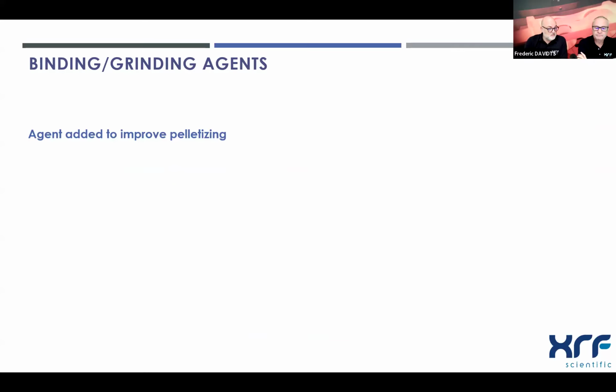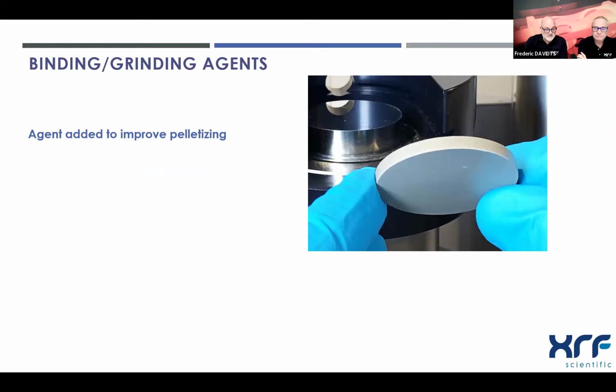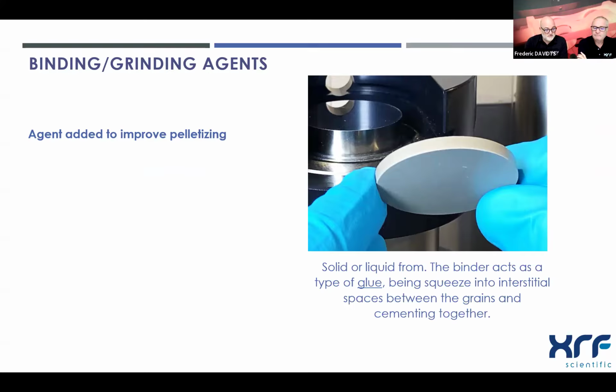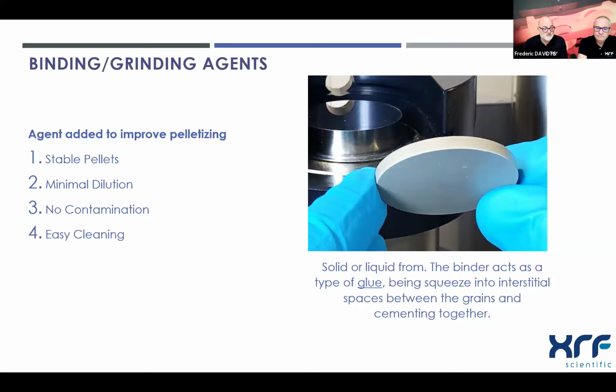So now let's speak about the binding and grinding agent. First, what do they do? Of course they improve the pelletizing. So we can see here a nice pressed powder, fully homogeneous. The binder, the grinding agent, could be a solid or a liquid. The binder acts as a glue, in fact, squeezed into the interstitial space between the grains and cementing all the grains together. So what we want is to have stable pellets. We want minimal dilution, like you explained, about the intensities, for the light elements for example. No contamination by the binders or the grinding agent, of course. Easy to clean, so easy to release the tablets from the die. And no moisture, because of course we don't want to analyze water, but also, if we work under vacuum, we don't want the pump taking too much time to create the vacuum in the analytical chamber.